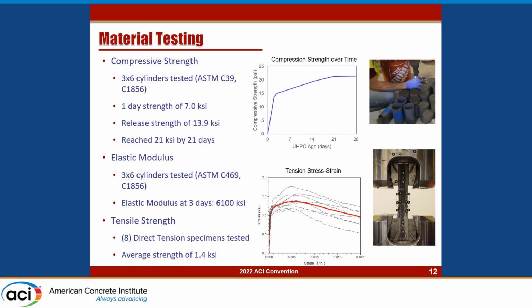We tested more cylinders for the elastic modulus, where we got about 6,100 KSI at 3 days. And then tensile strength, we tested 8 direct tension specimens like this. They're 2-inch by 2-inch bars where we directly pull. And this is the stress strain curves for those tests, with the red being the average curve. We got an average strength of about 1.4 KSI. So all of these numbers were very much within our expected range based on our previous UHPC experience, both with this material and other UHPCs.